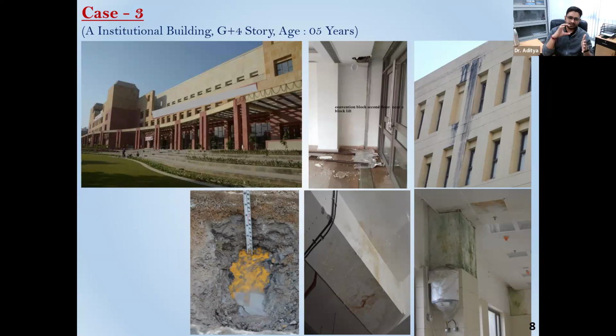So what is generally done is that at the terrace level, a thermal insulating puff is given in order to provide thermal insulation to the lower stories, and then a waterproofing arrangement is done. So in this place, they have done the thermal insulation puffing, but after that, the waterproofing treatment, basically a channelized polymer composite layer, is provided in order to channelize any water seeping through the RCC slab. It will basically go toward the slope. That's what it is supposed to do, but that was actually not provided. Maybe it was missed, or maybe it was intentionally missed. But because of that, what was happening?